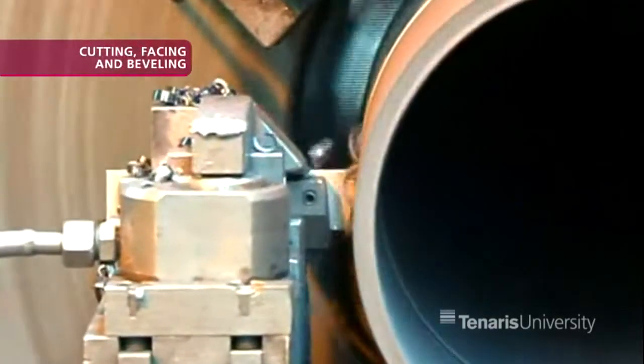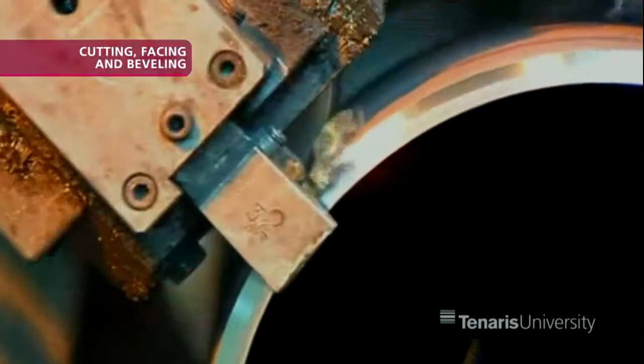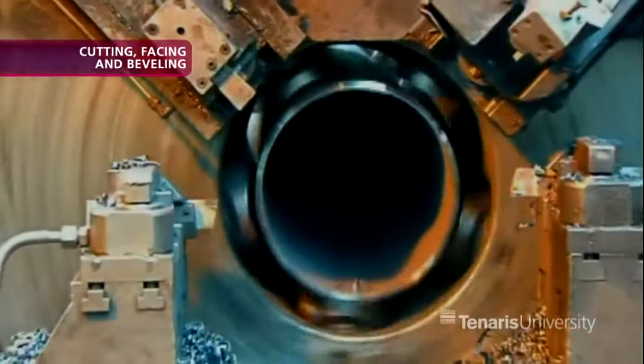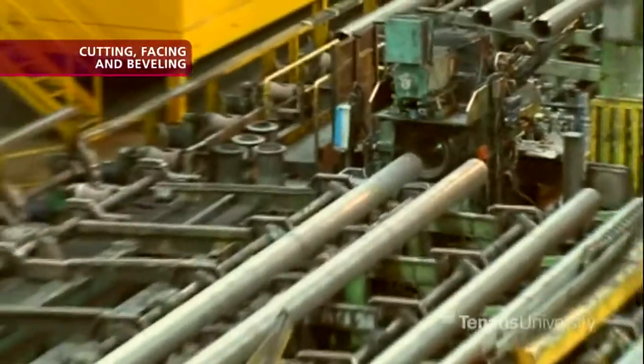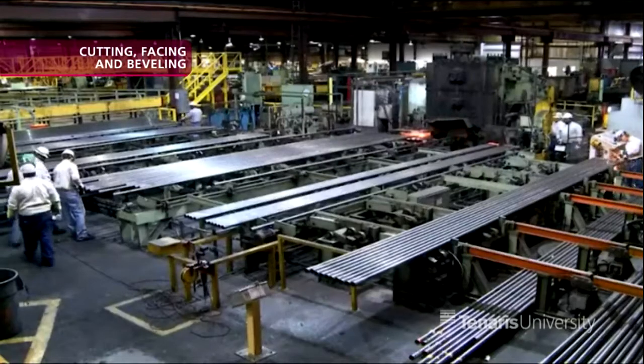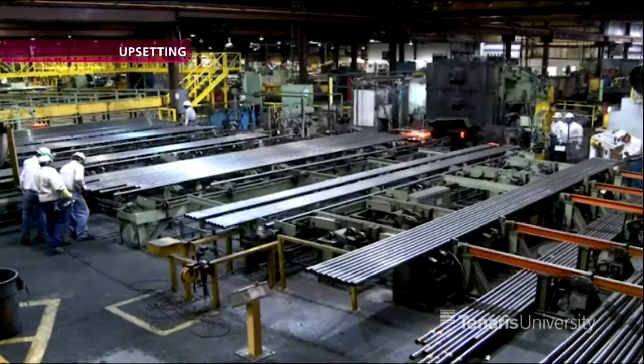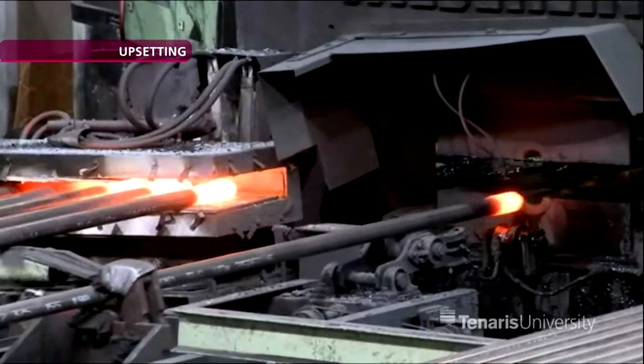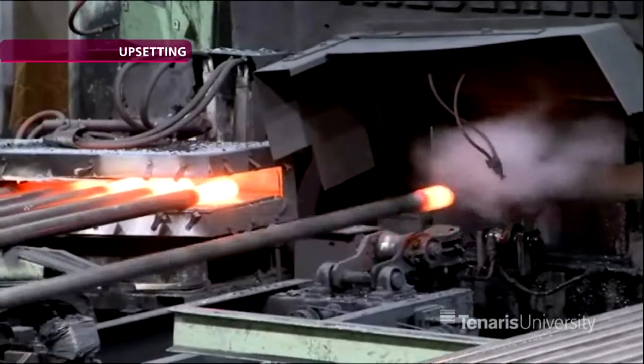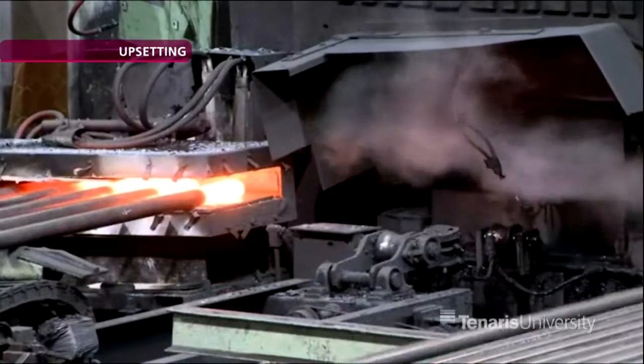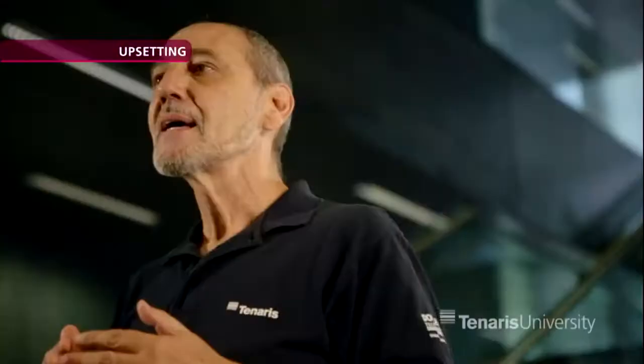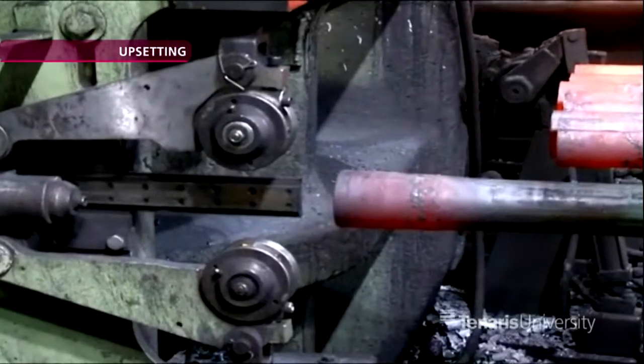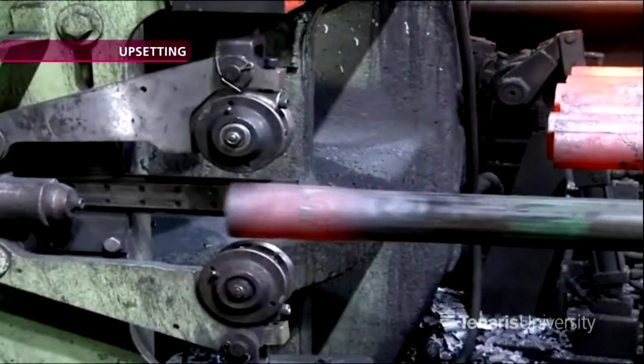In this stage, the tube is cut to the final length, faced, and beveled before threading. The purpose of the bevel is to help the beginning of the threading operation. Another process is the upsetting. The main objective of upsetting is to increase the wall thickness at the end of the tube to allow further threading operations. Upsetting consists of increasing the wall thickness of the tube ends by a forging action with two half dies and a punching mandrel into the tube.